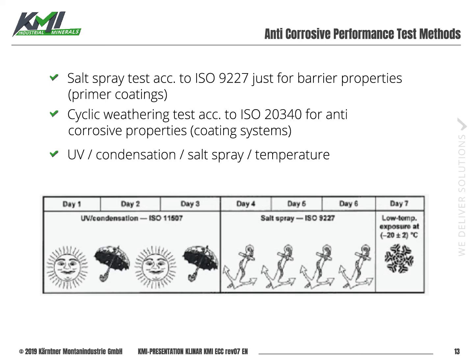Then you have the typical salt spray test for another 3 days, and then you have a low temperature exposure at minus 20 degrees C for 1 day, and then you start the cycle again for 25 cycles, 25 weeks, which means it's a 6-month test, which is a quite harsh test developed mainly for harsh marine environments.